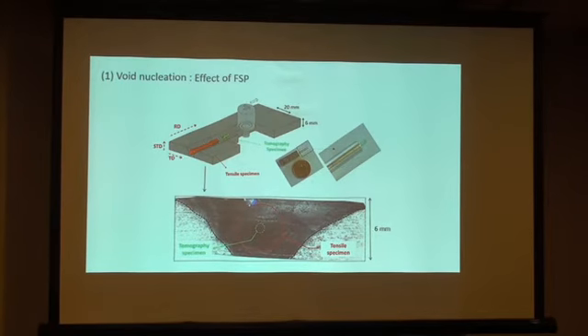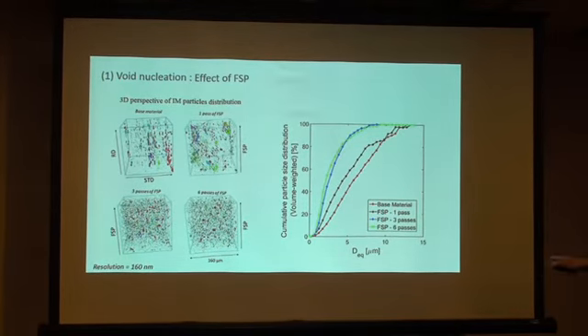So now, to study the effect of friction stir processing, as I said, we have done this processing over multiple passes, and the tensile specimen was extracted within the stir zone, and we also extracted a little tomography specimen at the center of the tensile test. And what you see is that this is the base material, with big particles clustered along the rolling direction, and then after one pass of FSP, you see that the spatial distribution has been modified. However, there are still a lot of big particles, and then after 3 and 6 passes, the distribution is completely different, and you have a huge increase in density of particles as you have broken them into multiple fragments.